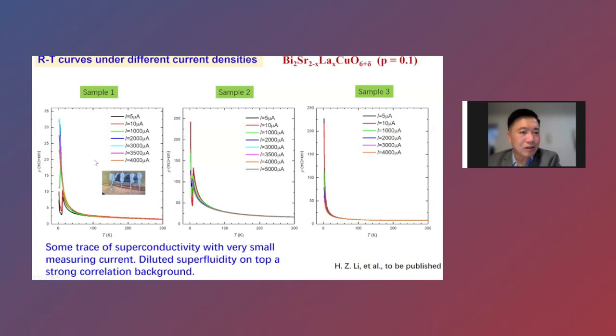So first, let me show you the transport data for this 10% doping, supposed to be at the boundary. So you can see that for this single crystal, if we measure resistivity when the current is large, then we see a huge insulating behavior. However, when we lower down the current, then the superconductivity somehow sets in. Also, the transition is not complete. Okay. And for some samples, even with the smallest current, we don't see this transition.